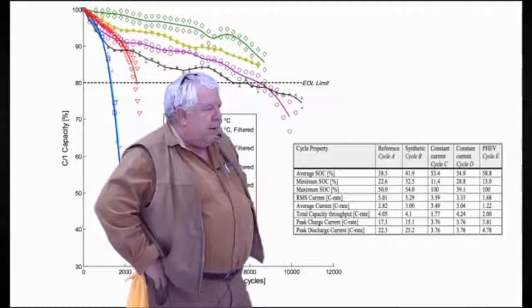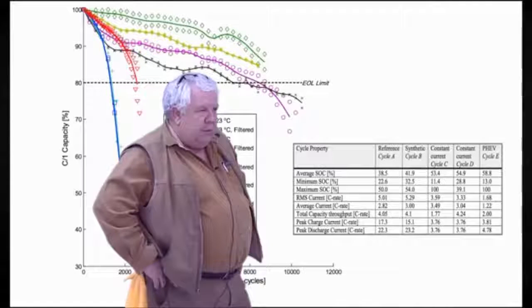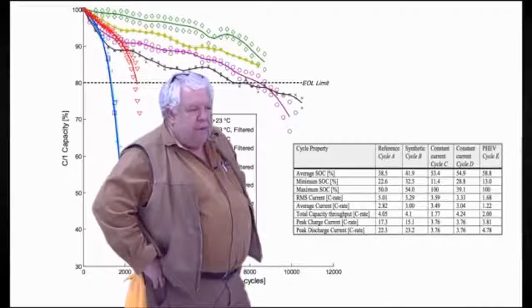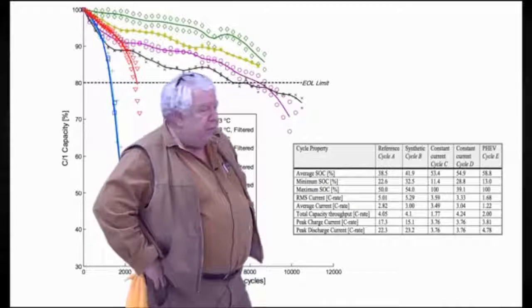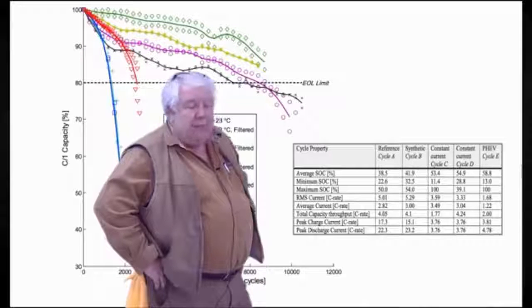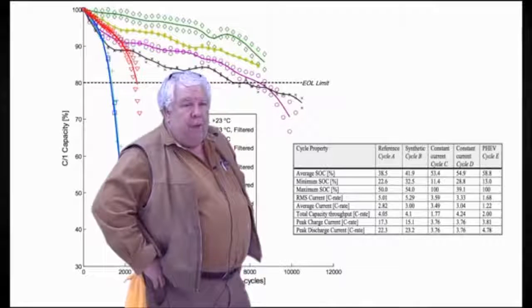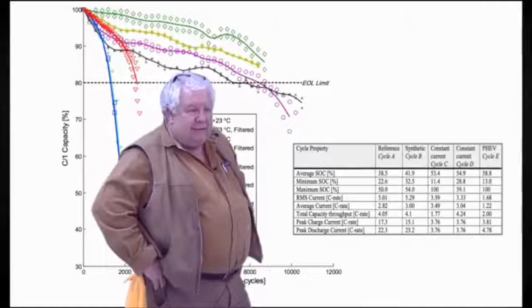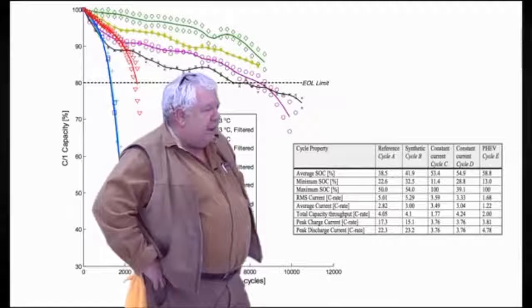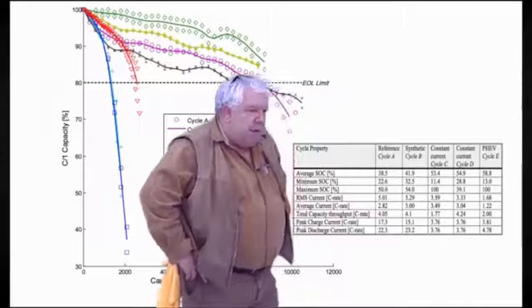In this, it's absolutely definitive, with a huge number of cycles and a clear delineation of temperature from 23 to 35 degrees and a big separation in the results: a higher temperature up to a point actually extends the life of the cells, increases its performance, increases its capacity, and it isn't always a good thing for lithium-ion iron phosphate cells.